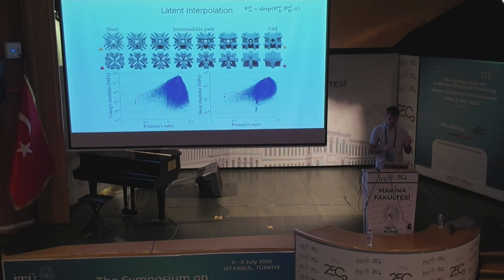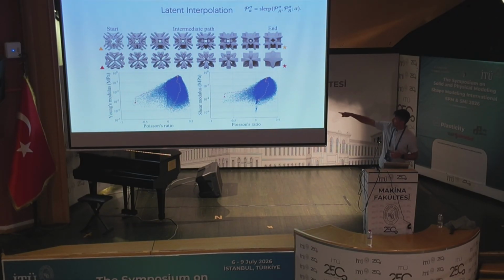So these models retain initially their truss topology, then increase the volume fraction to achieve higher Young's modulus values, and then gradually they transition into these plate configurations. And we also plotted the path in material property space, which I think looks quite reasonable.